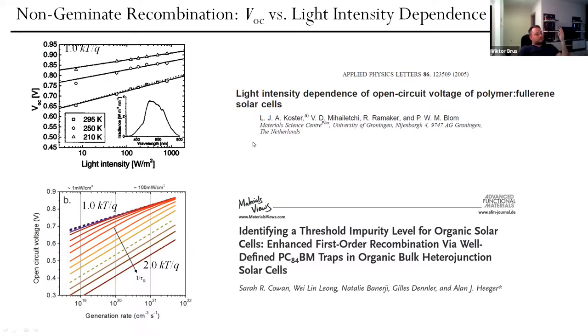So there is also non-geminate recombination, as you remember. Unfortunately, we lose charge carriers also after separation of excitons. Free charge carriers can also be lost. And one of the very simple and straightforward techniques to estimate the dominant non-geminate recombination, which may consist of bimolecular, trap-assisted in the bulk and at the surface, is the light intensity dependence of open circuit voltage. So it was shown that for pure bimolecular recombination, when we have open circuit voltage versus generation rate or light intensity, because these are proportional to each other, so it's not so important which parameter we take, the slope of the VOC dependence on the generation rate or light intensity should be equal to 1 kT/q.